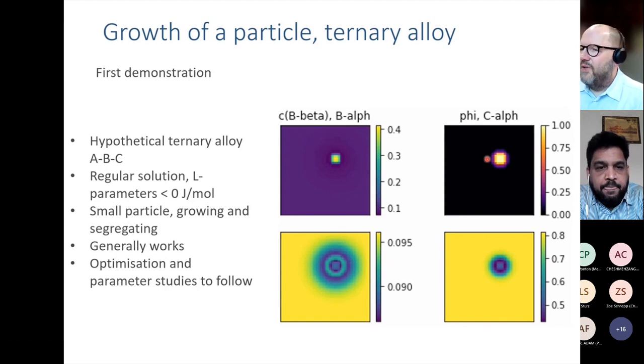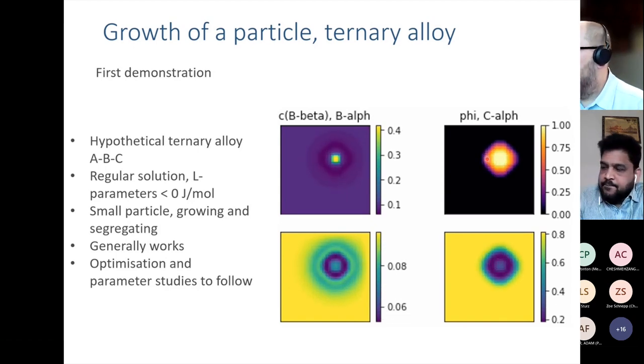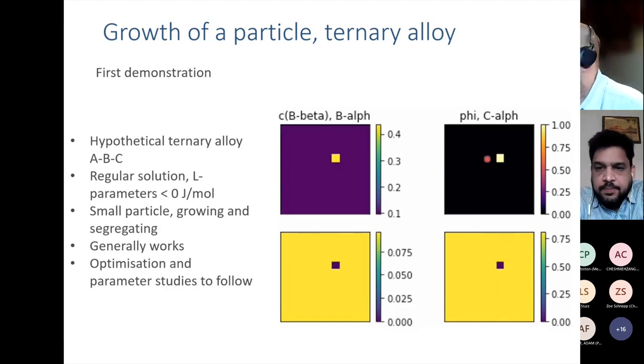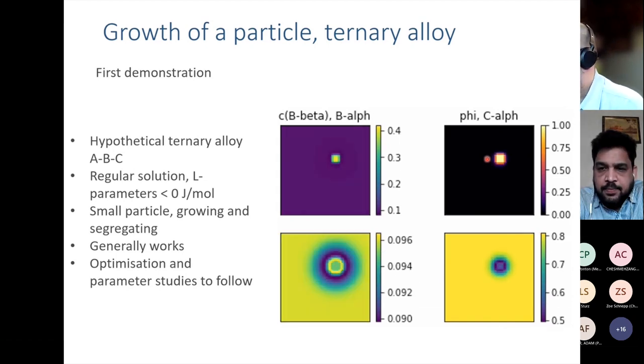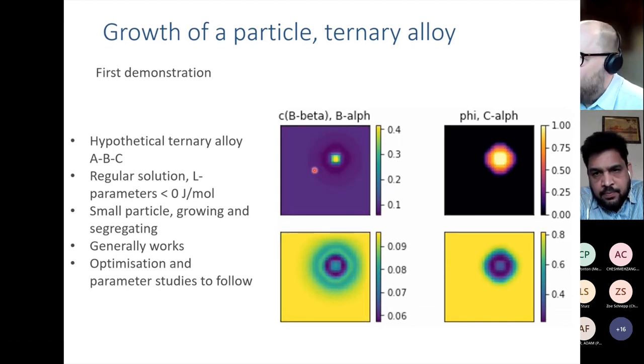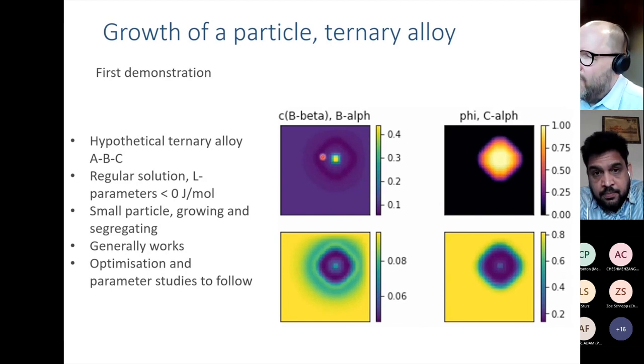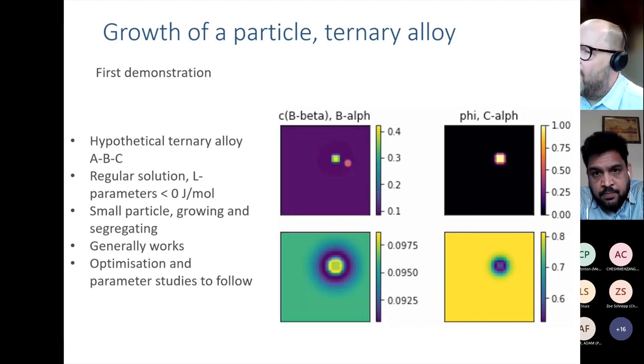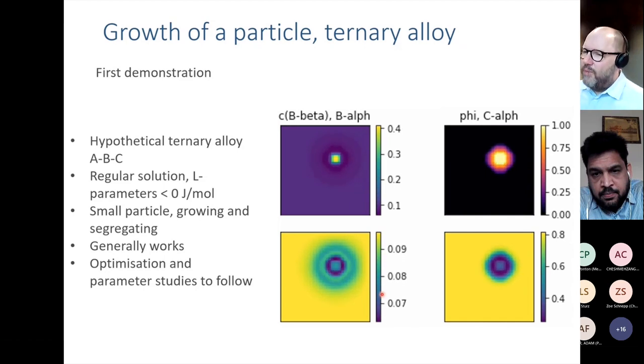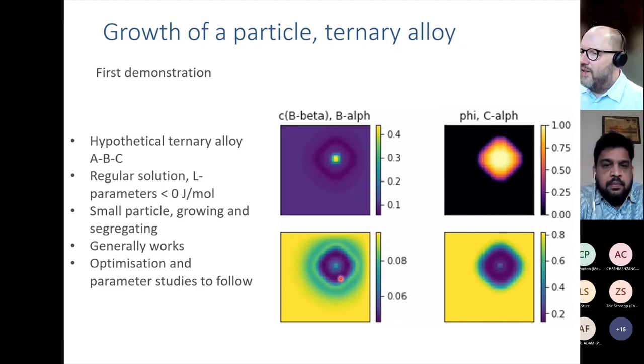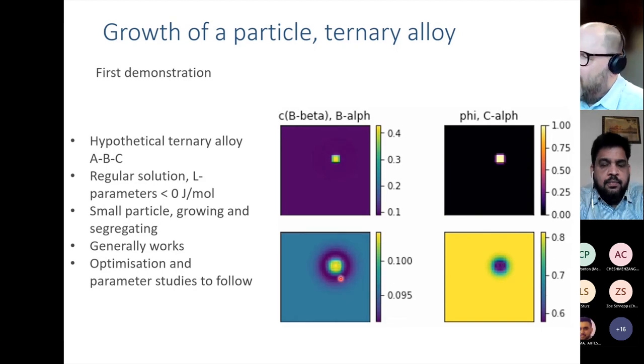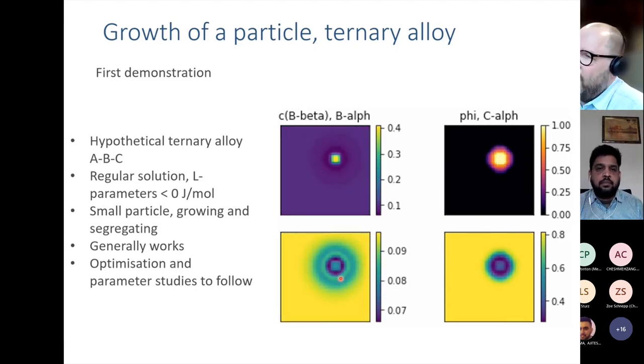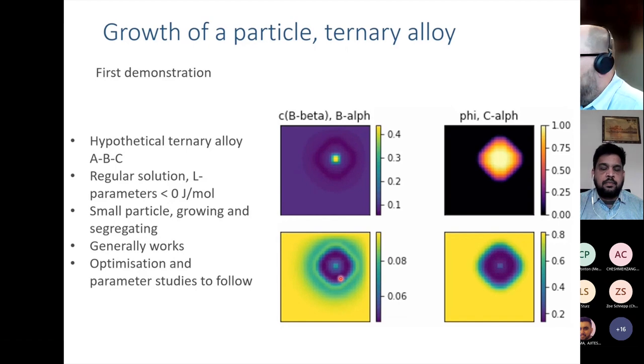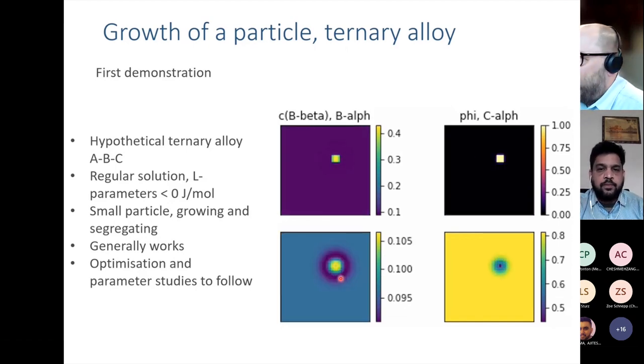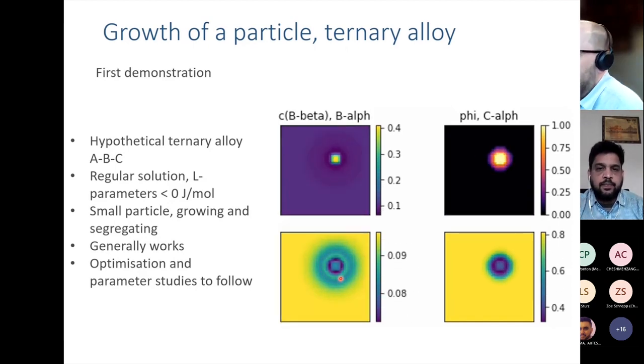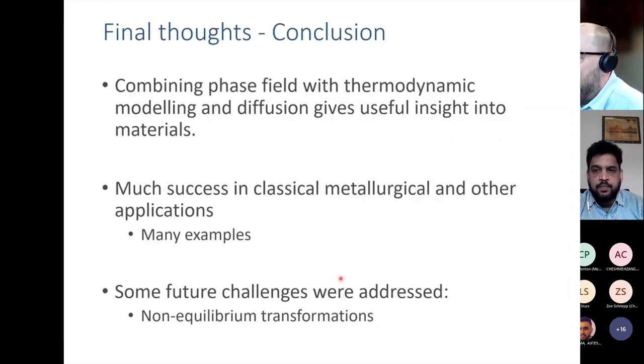Here, on the other hand, is a system where I start with a small particle, include the thermodynamic interaction, and simulate the growth of the particle. And we see the particle growing, it's segregating. Up here is the total concentration profile around this, and the element segregates. And down here, we have the composition profiles in the particle and the matrix themselves. So we get a response, the particle is growing and following that. We're not fully there. I still see a number of problems to solve and things I'm working on, but I think we're on the right track with that.